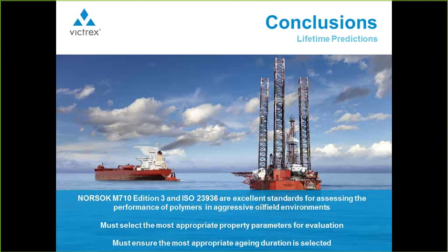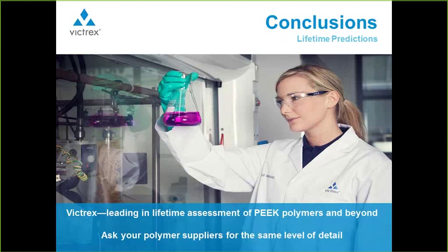And finally, early termination of aging can lead to very significant overestimates of lifetime and the maximum usage temperature. So I hope that we've communicated that certainly at Victrex we believe we're leading the way in developing lifetime assessment for PEEK and other polyaryl ether ketone polymers.